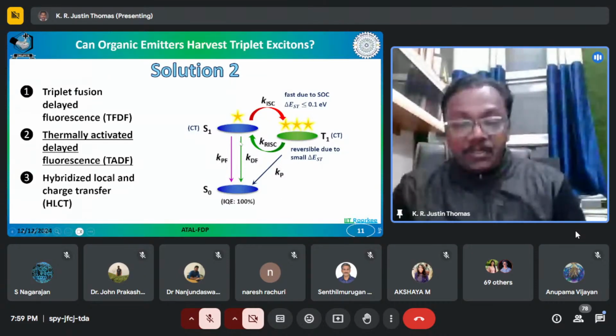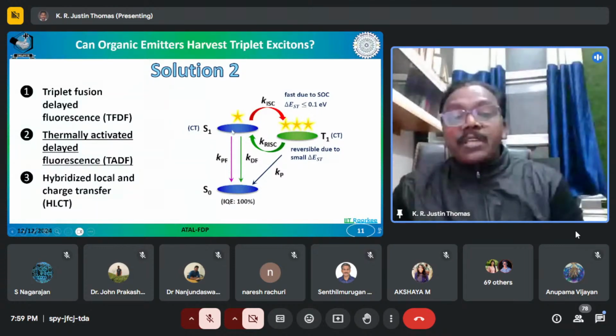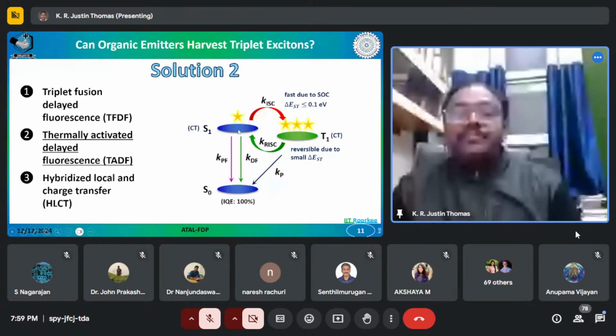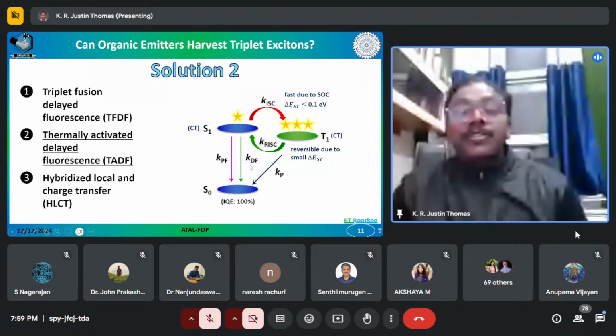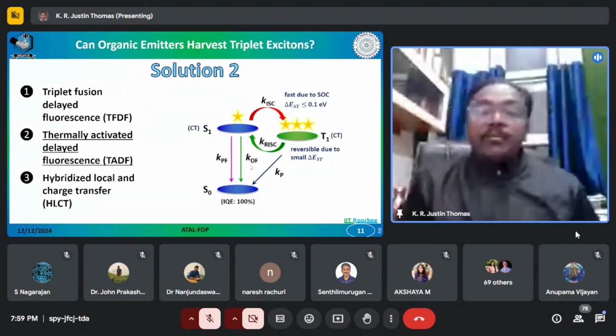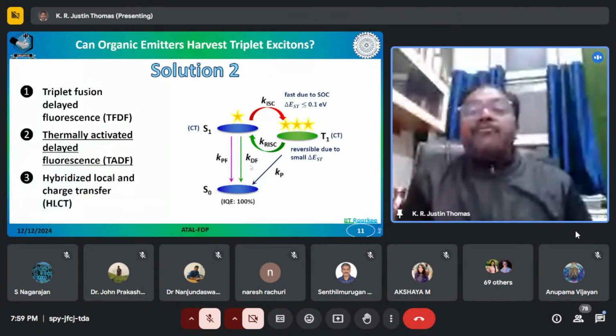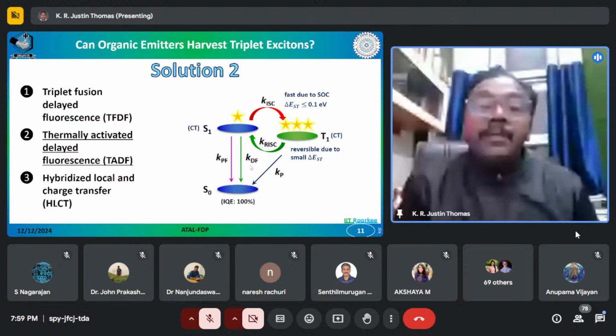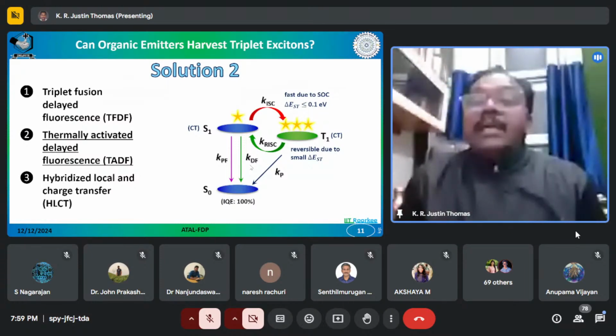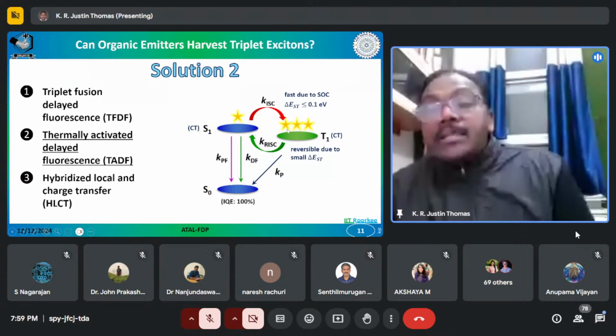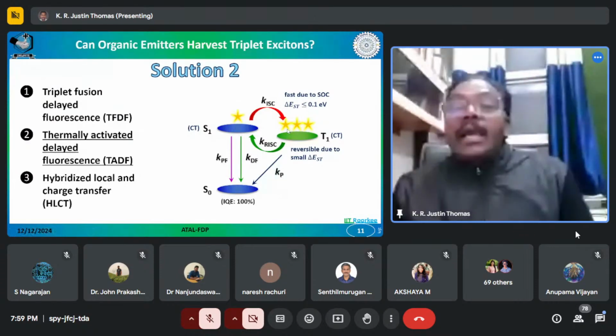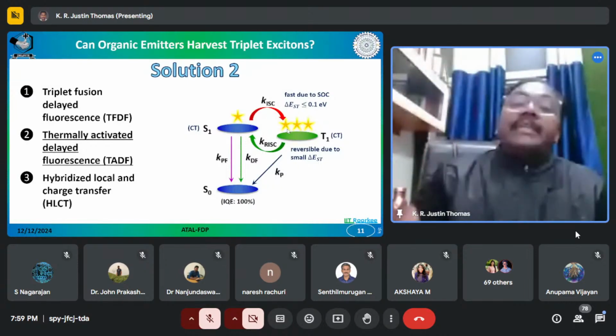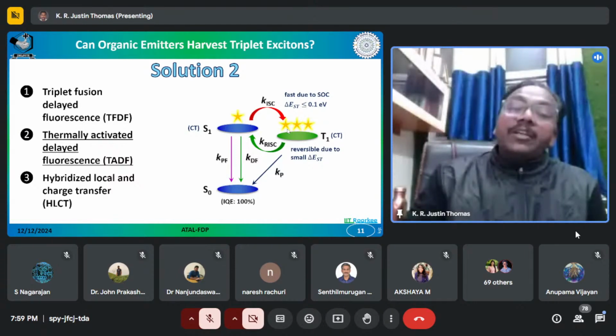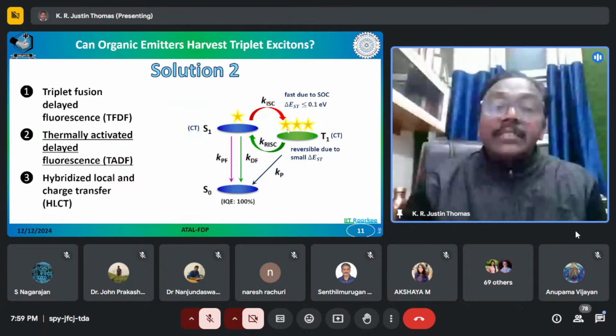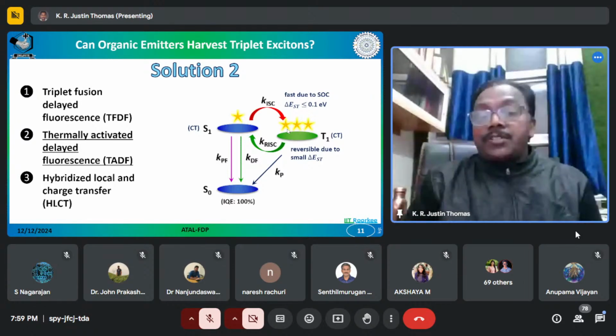Then it comes to the ground state with the delayed emission from the same state, that is the S1 state. So the characteristics of prompt fluorescence and delayed fluorescence will be almost the same. They will have an overlapping profile, but the lifetime of the prompt fluorescence will be very short compared to the lifetime of the delayed fluorescence. Why? Because the molecule goes by inter-system crossing to the triplet state, which takes some time, and then comes back to the singlet excited state, which takes some time, and then it comes to the ground state. So it will obviously be larger than the lifetime of the prompt fluorescence.